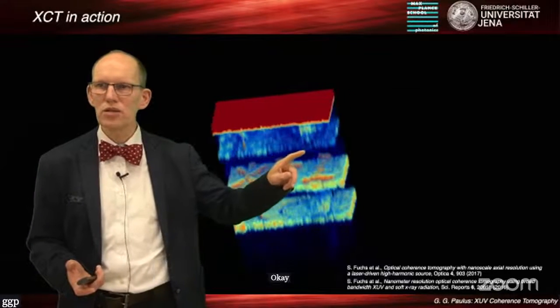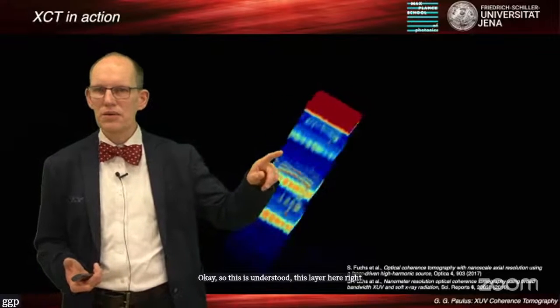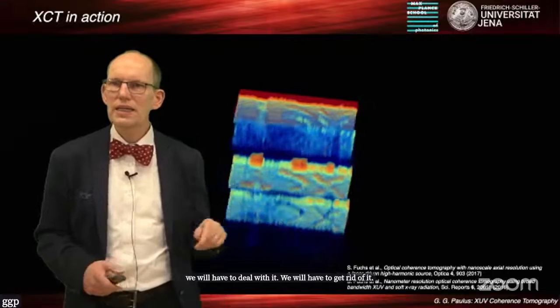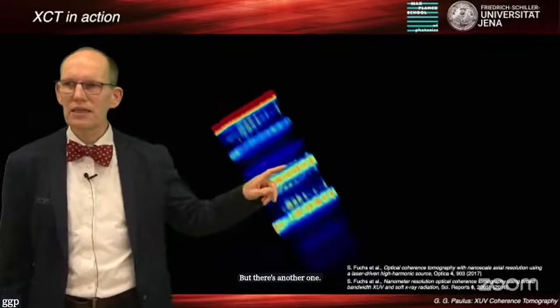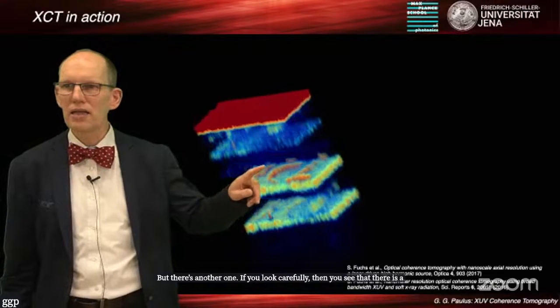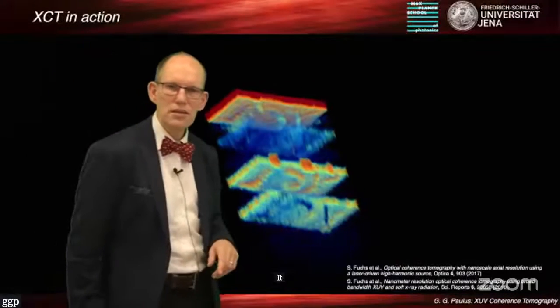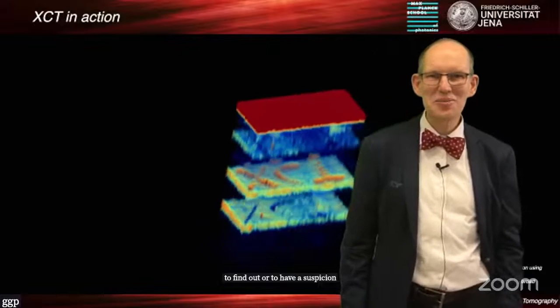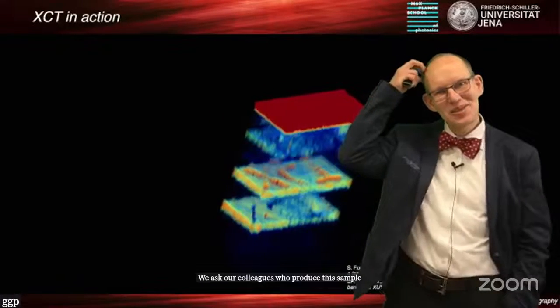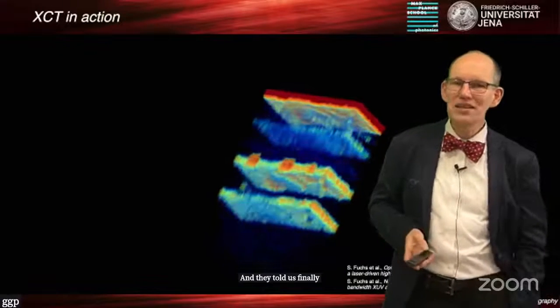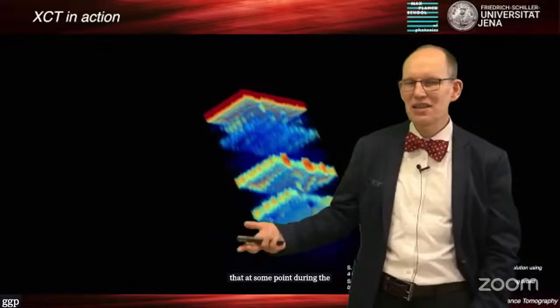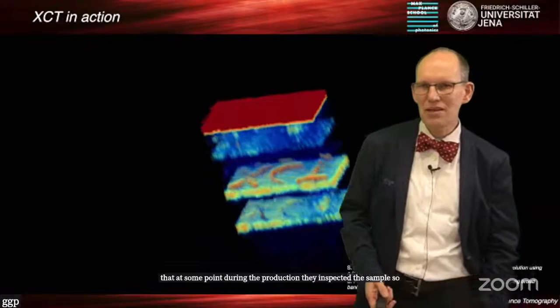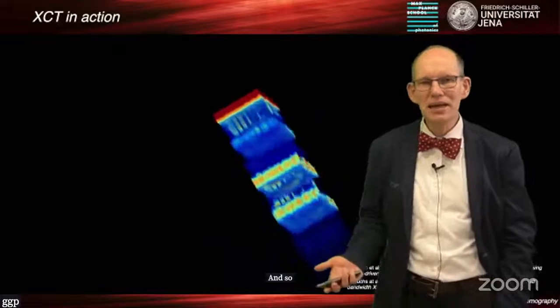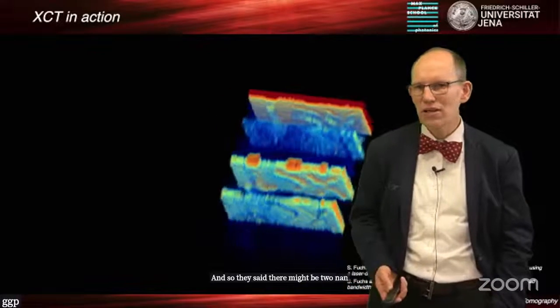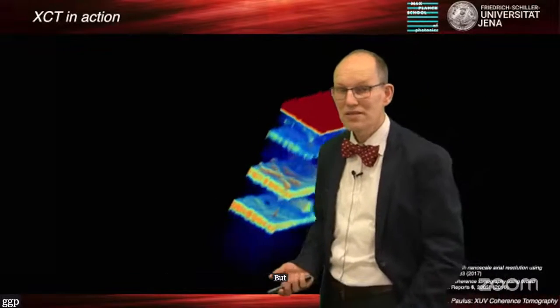Okay, so this layer is understood. We will have to deal with it, we'll have to get rid of it. But there's another one. If you look carefully, you see that there is a faint additional layer. It took us a while to have a suspicion. We asked our colleagues who produced this sample, and they finally told us that at some point during the production, they inspected the sample, so they broke the vacuum. And so they said there might be a 2 nanometer thin layer of oxide, but you'd never be able to see it.